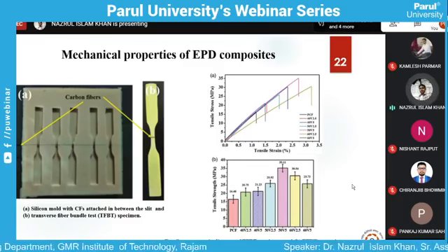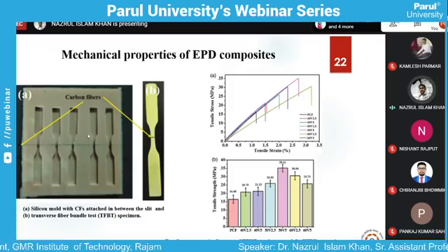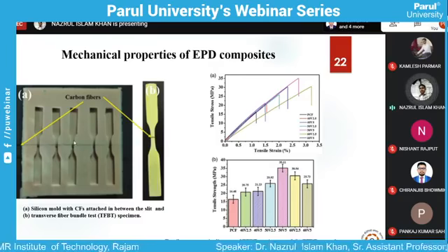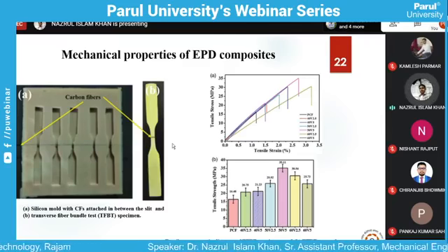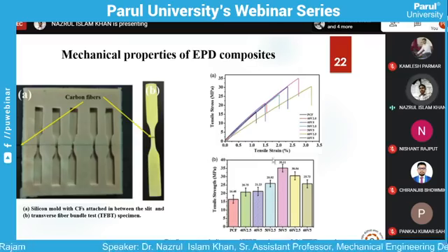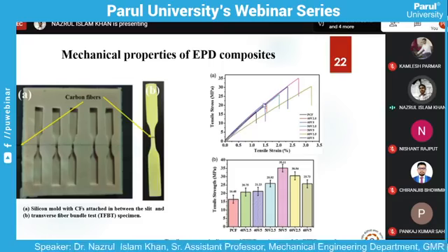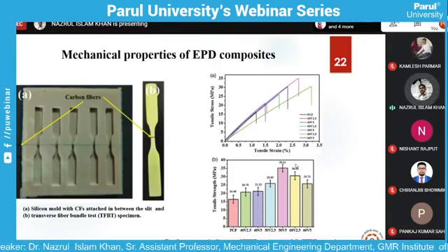So if you have better adhesion, then you will have good tensile properties. If you have poor adhesion, then the tensile property will be reduced. So in transverse direction, using the TFBT test, we are able to calculate how the interfacial adhesion between fiber and matrix is taking the role. For that we found that 50 voltage and 5% of carbon fiber nanoparticle gave us the optimum result, that is 35 megapascal.